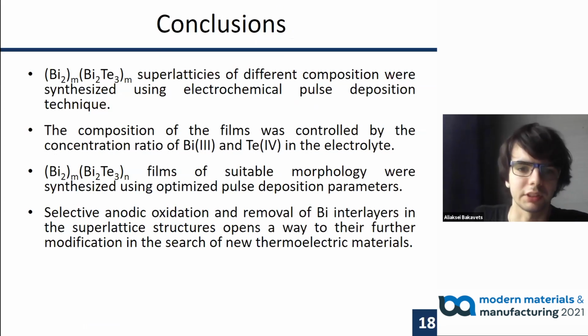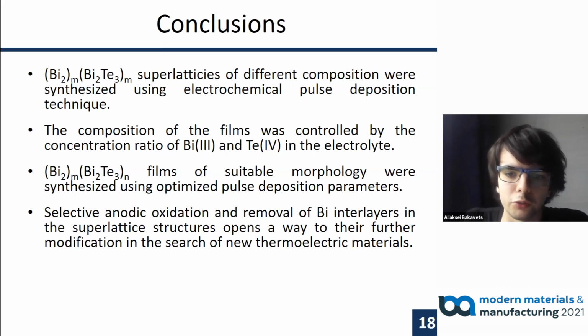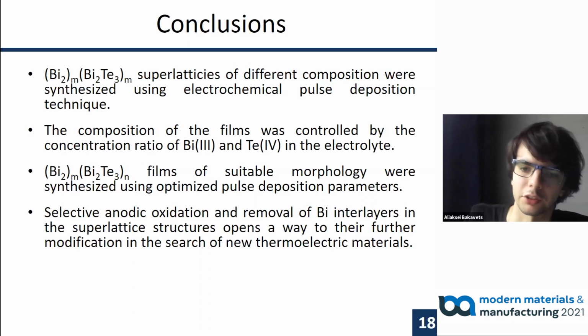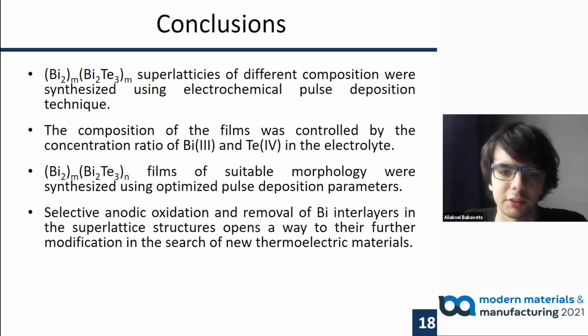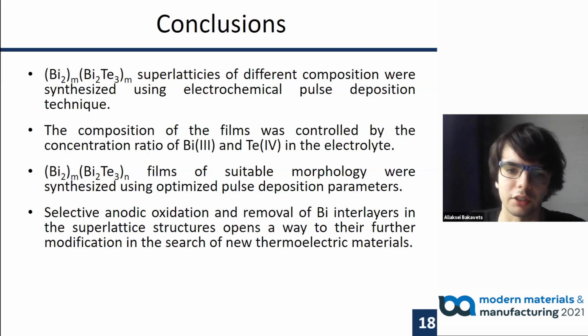So, concluding my presentation. We developed the electrochemical way of synthesis of layered superlattice structures with controllable composition composed of Bi2Te3 layers and bismuth bilayer building blocks, verified their structure by X-ray diffraction, X-ray photoelectron spectroscopy, and high-resolution electron microscopy, and optimized the deposition process to produce films with good morphology required for thermoelectric applications.